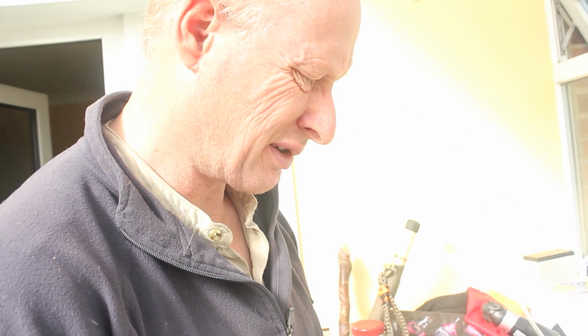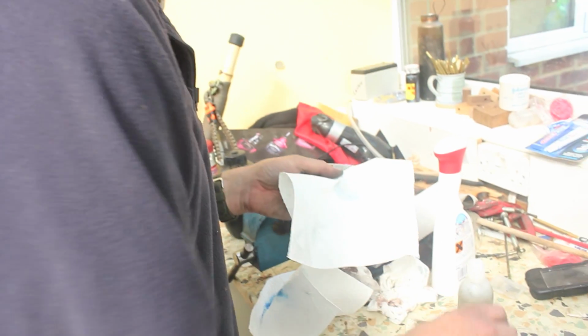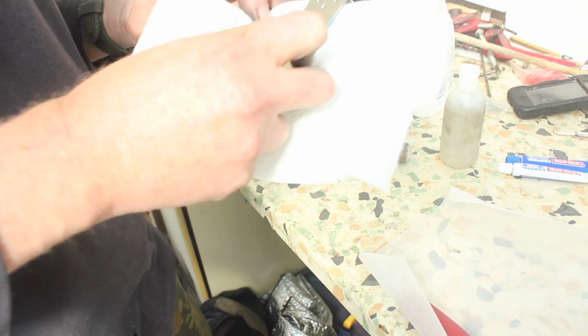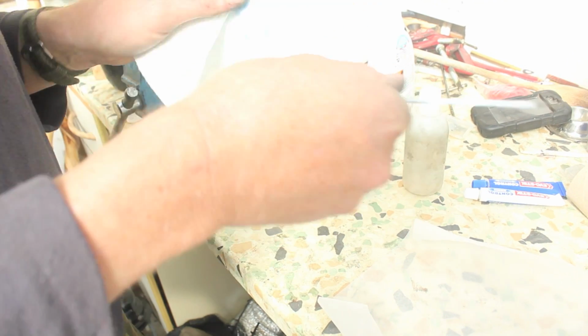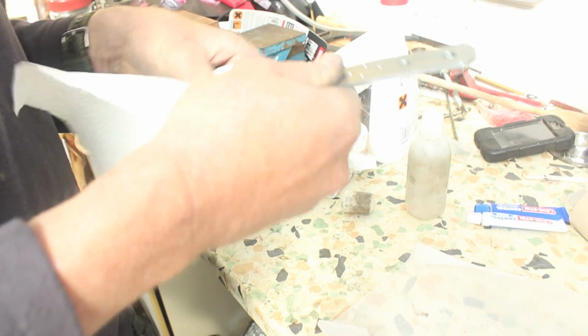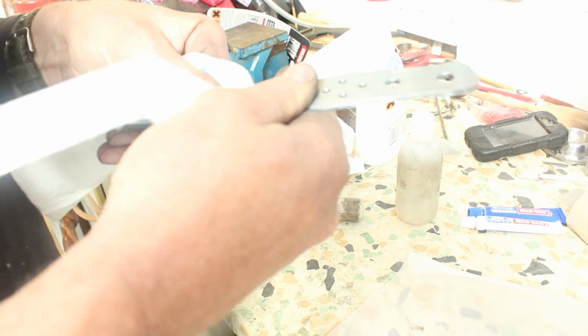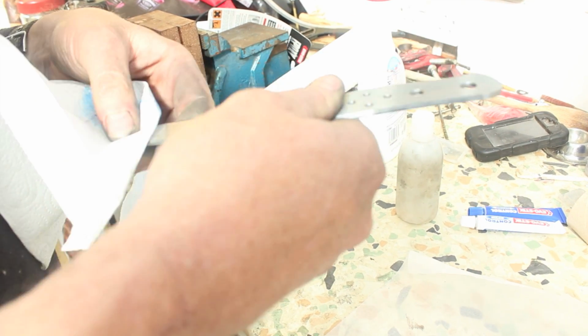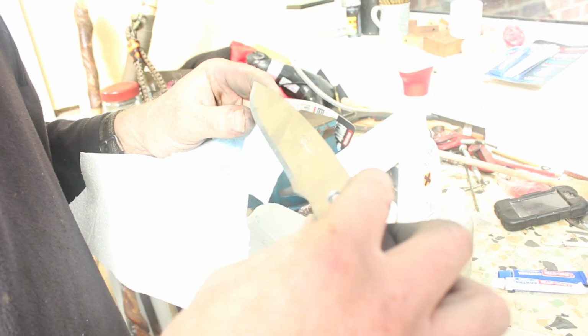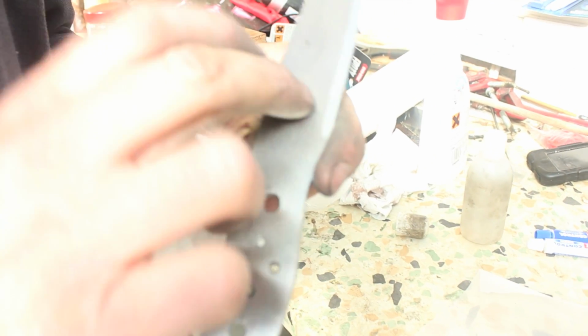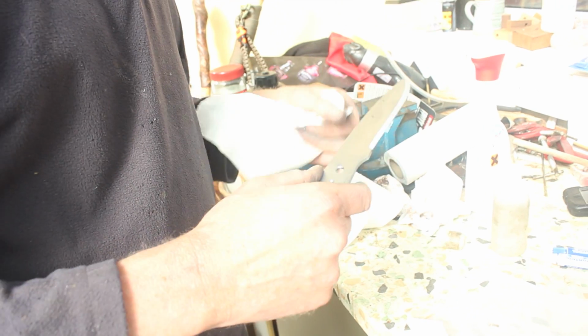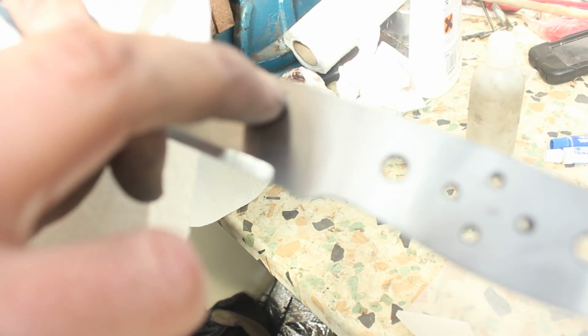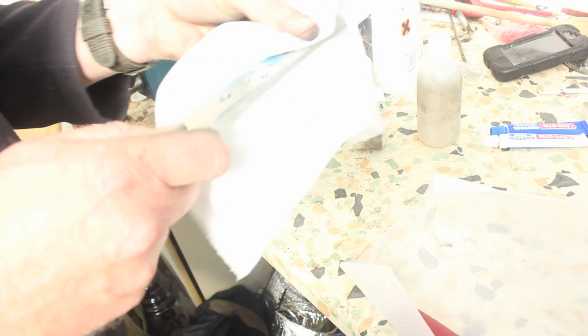It saves it from being burnt on, because in the kiln this is going to reach quite high temperatures, and it's just a good idea to have your knife as clean as you can get it before it goes in. Get any of the engineer's glue off, any bits of debris and grit. I haven't cleaned up this side yet, and the reason why is because when you stamp the logo sometimes you get a back mark as well. I can clean that up after heat treat. And those little marks, they'll come out when we grind up afterwards. So there we are.